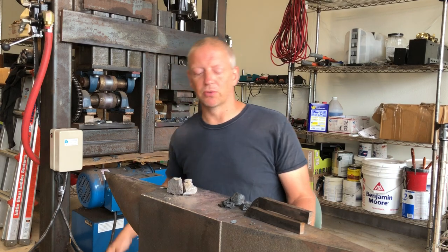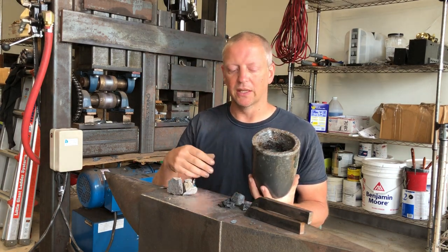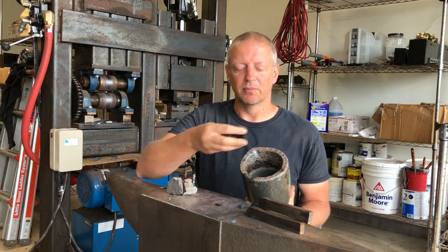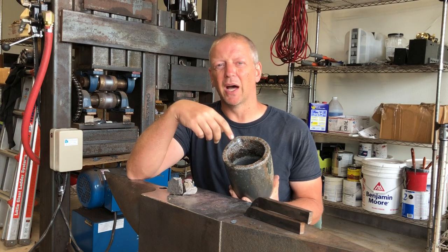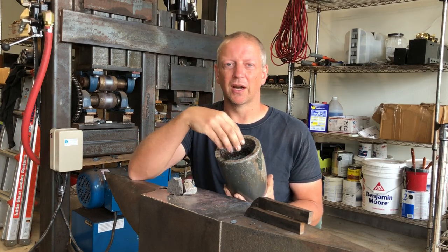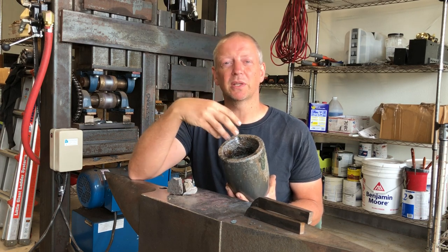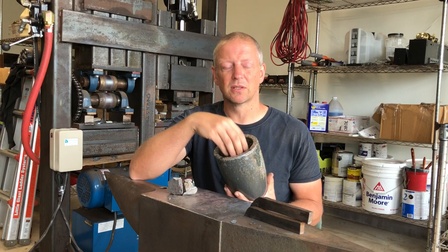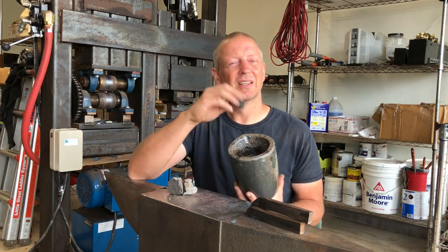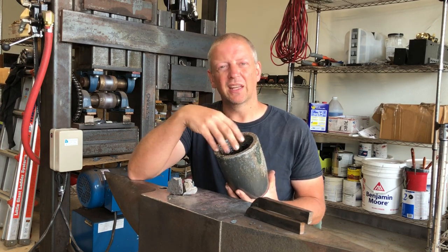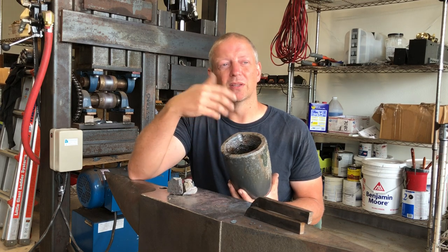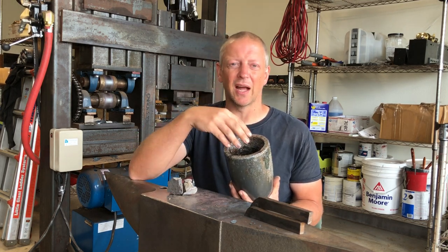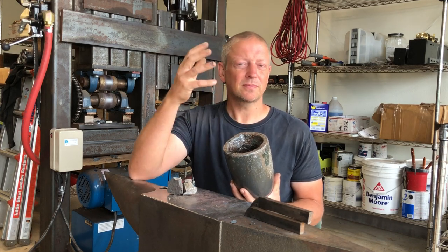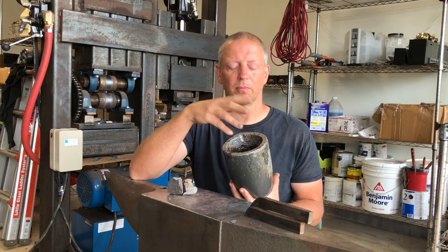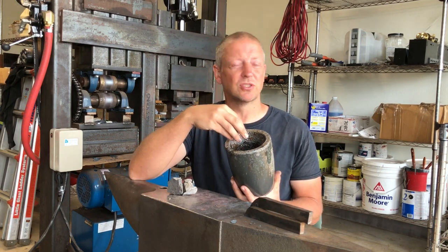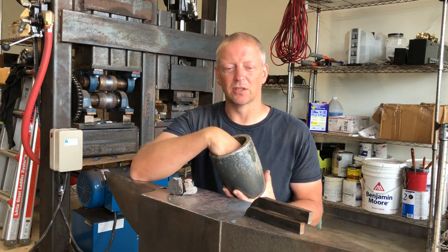So I'm going to bring my crucible back for a little bit of demonstration, as a visual aid. If I'm using charcoal, I will have measured out how much I want, and it goes at the very bottom of my crucible, and then my wrought iron, whatever it is, goes on top of it, preferably in relatively small pieces. I also want my charcoal to be in relatively small pieces. Think of that lower layer, it's good if they mingle together some. The reason for this is that you're dependent on contact between the charcoal and your wrought iron or mild steel for the carbon to pass through into your steel.